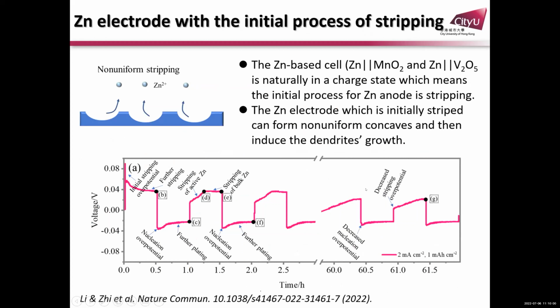And recently we noticed that for zinc batteries, typically we fabricate zinc manganese oxide and zinc vanadium oxide batteries, and when you fabricate the batteries, they are naturally in a charged state, then you start to discharge. Discharge means zinc will start to dissolve. That means in the zinc battery, typically you start from the charged state and zinc will be stripped first, then plated back, right? Then we studied the stripping process in detail.